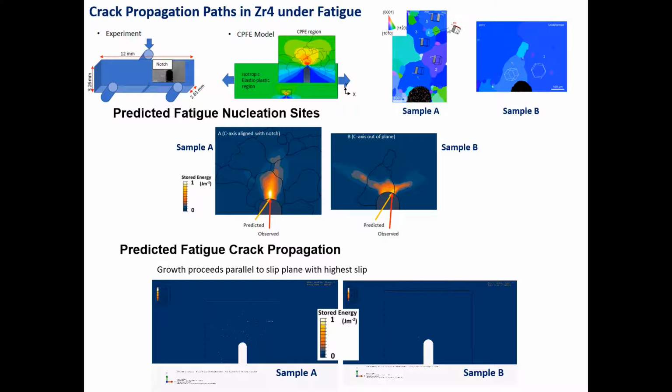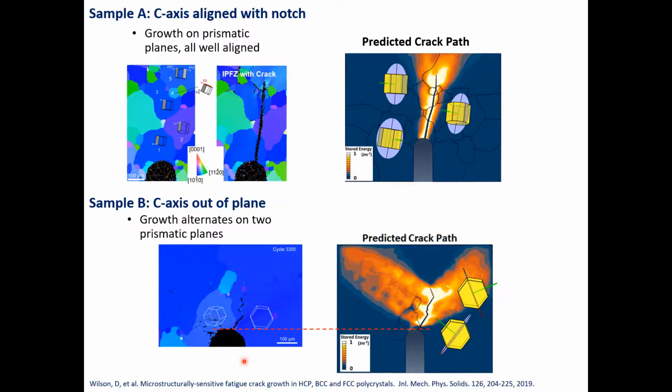Sample B is the case that's a bit more ductile, where the crack grows on the prism planes, but parallel with the Burgers vector, but at differing rates and a different path developed by the crack as well. Let's have a look at those in a bit more detail. The next slide, where we can see the experimental observation directly and the model in comparison. And here, so the very straight crack for that case, of course, parallel to prism, and down here where the crack clearly oscillates within the single crystal, which is to a large extent what the model is replicating down here, and also the decreasing amplitude of oscillations when the crack gets longer, both in the model and the experiment.